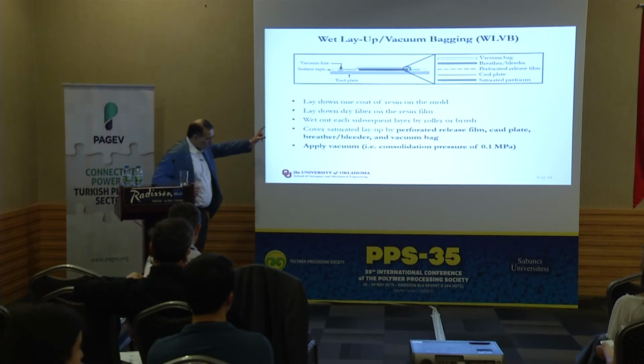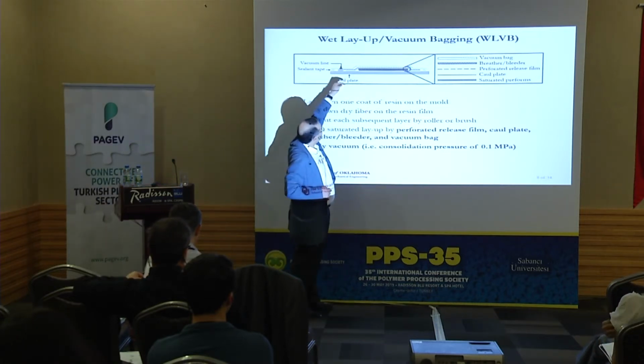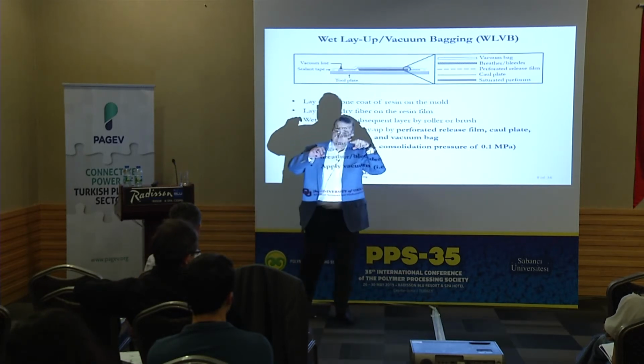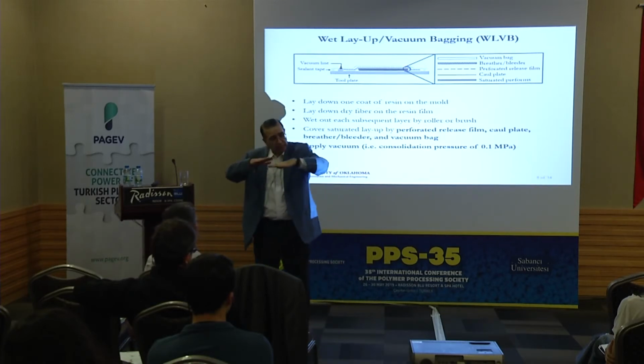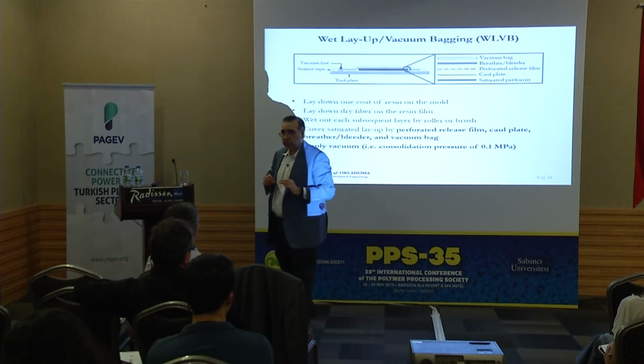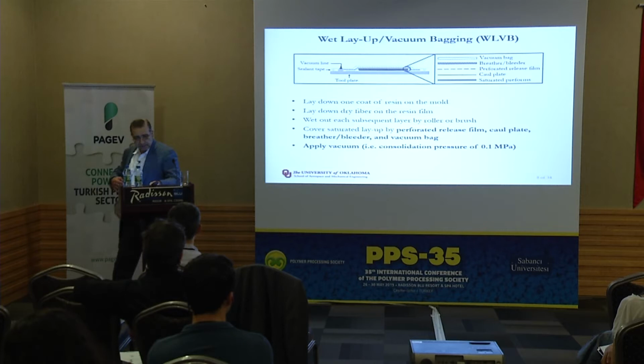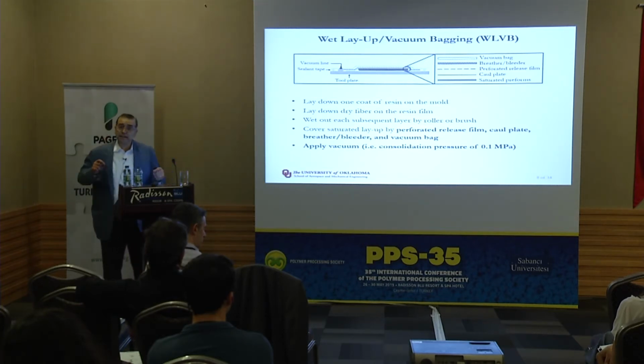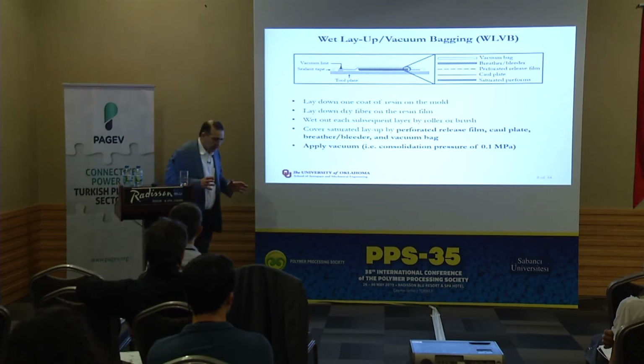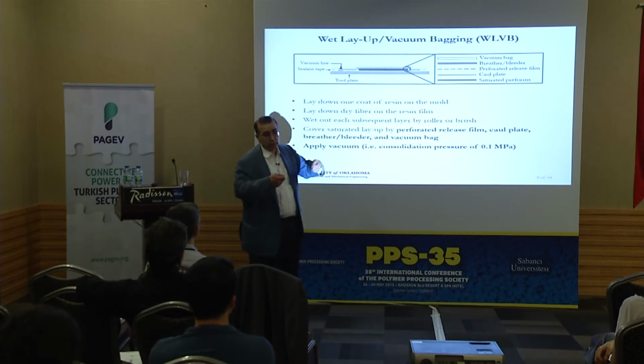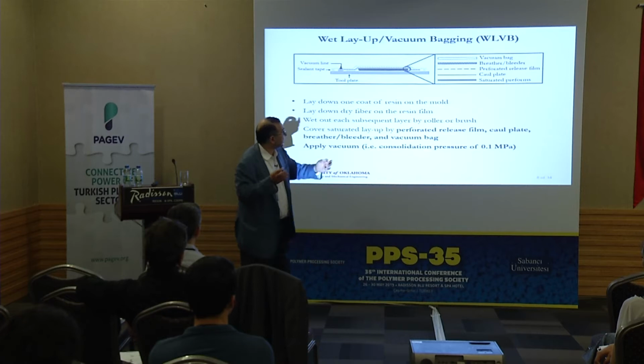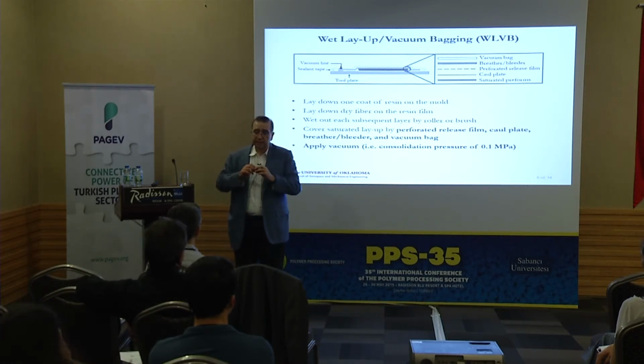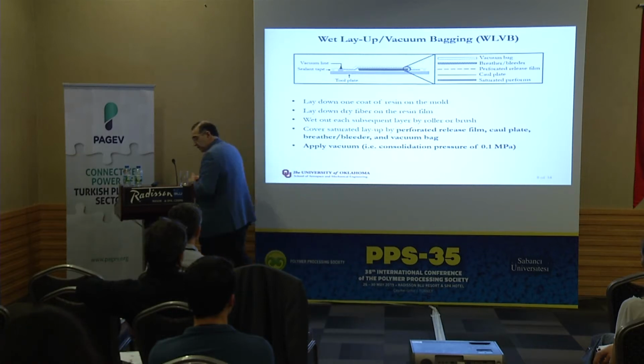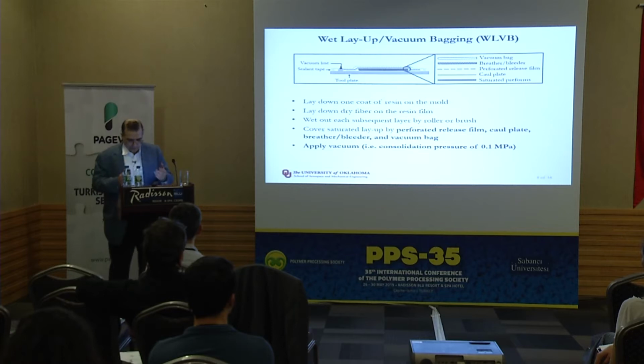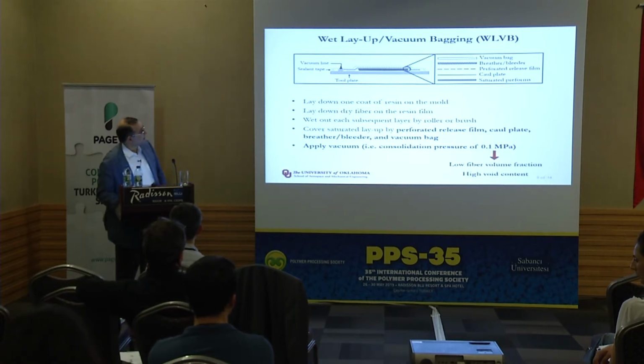And then the vacuum bag, you have to seal it all around. You have seen it in the video, especially if you have thermocouples going in. The thermocouple needs to go through the sealant, so you need to make sure that you tape it and that there is no leakage. Thermocouples and things going inside the vacuum bag are always a potential area for leakage. Now, at room temperature, everything may look good. If this is an autoclave, you put it in the autoclave and cook it. At high temperature, these sealant tapes become soft. They give up their rigidity a little bit. So at room temperature, you can do your leak check and it might be just fine, but at higher temperature you might have leaks. So you need to pay attention to sealing properly.